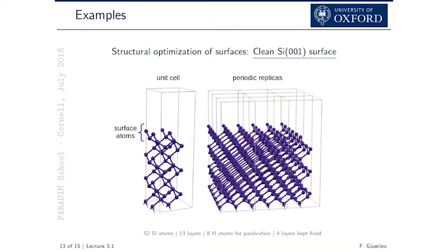So what you see here is that I place some hydrogens, because each silicon atom has basically 4 electrons, and if you don't place hydrogens, you would have some dangling bonds. So that's basically like a passivation step. Now, there is also passivation in DFT calculations. That's to make sure that the system is insulating and you don't have any states in the gap, which would be very odd to study. On this side, instead, we leave it like it is, because that's the structure in the experiments people started from.